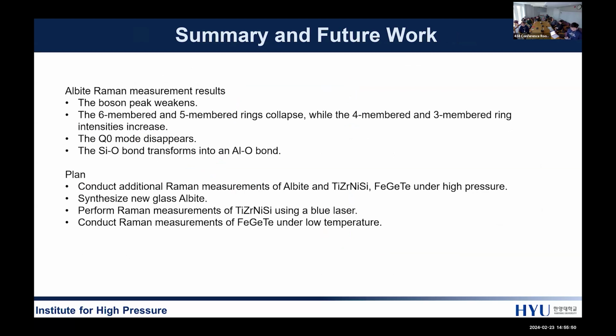The result reveals a reduction in the disorder-related boson peaks with increasing pressure. Additionally, the collapse of 6- and 5-membered rings into 4- and 3-membered rings, the disappearance of the Q0 mode representing individual silicate, and the transition from silicon oxide bonding to aluminum oxide bonding were observed. Further exploration of this phenomenon requires subsequent high pressure experiments exceeding 60 GPa.